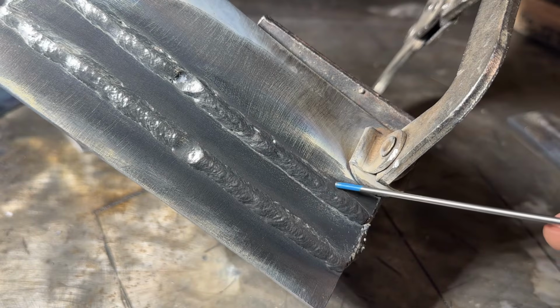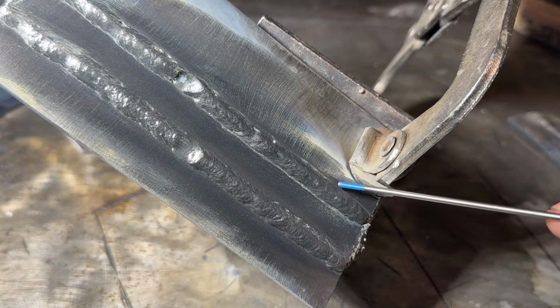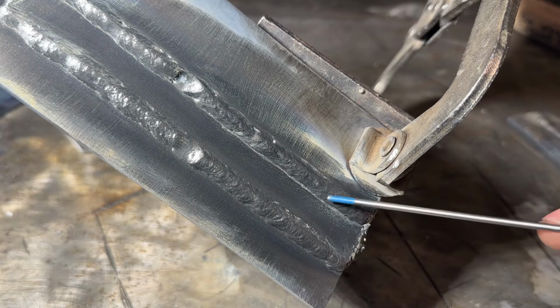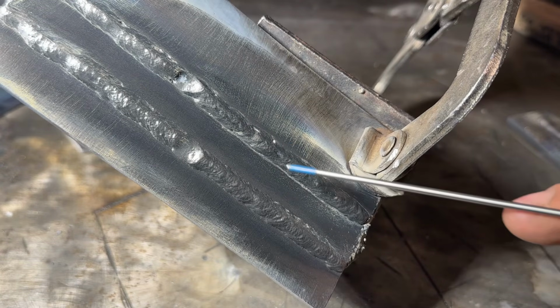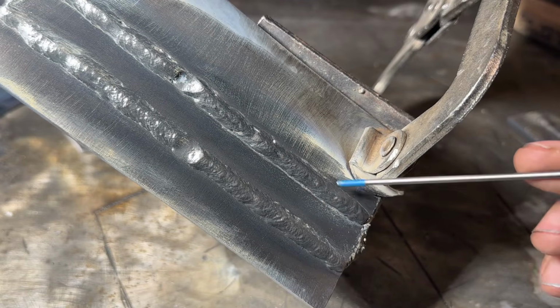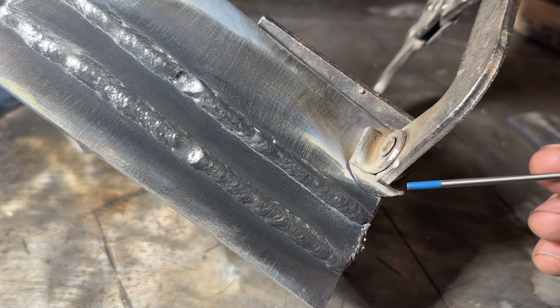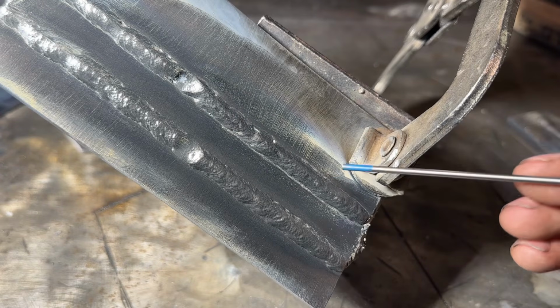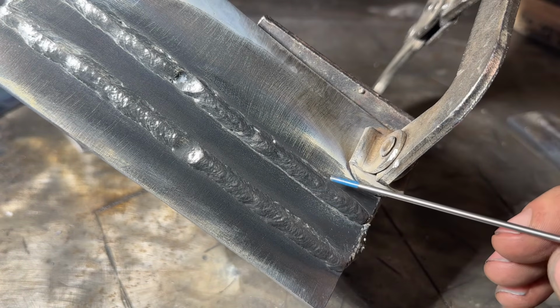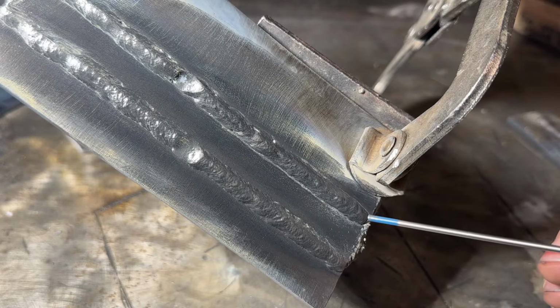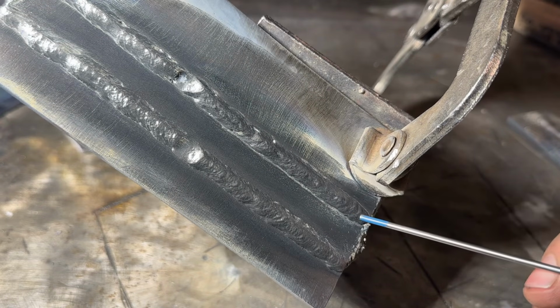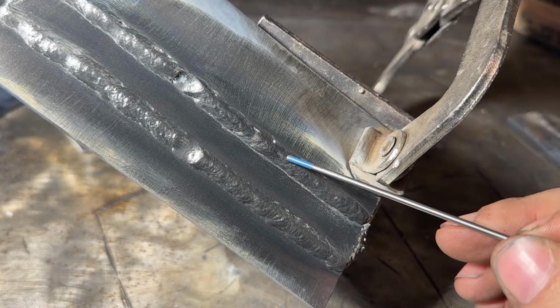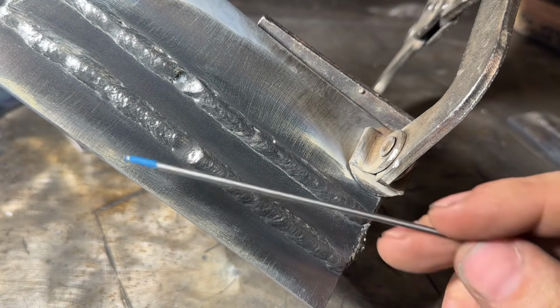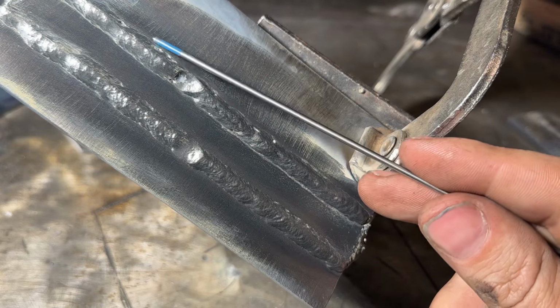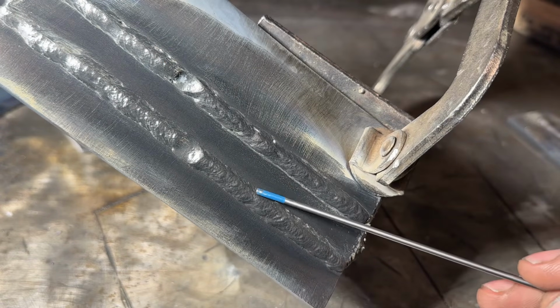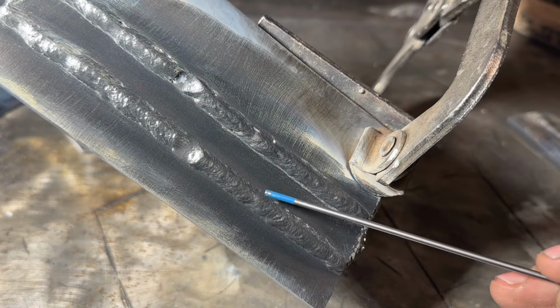So at this point, considering how much of this weld is exactly like what I would want, where it's not all crowned up and it doesn't really have any defects, I know that my settings, plus or minus 0.2 volts, plus or minus 5-10 inches per minute of wire feed, I'm dialed in. And then the final change is just going to be controlling my welds with how fast and consistent my movement speed is. But we're dialed in, and you can see how much more crowned up this first weld is, the second, much flatter. It still has a little bit of a round profile.